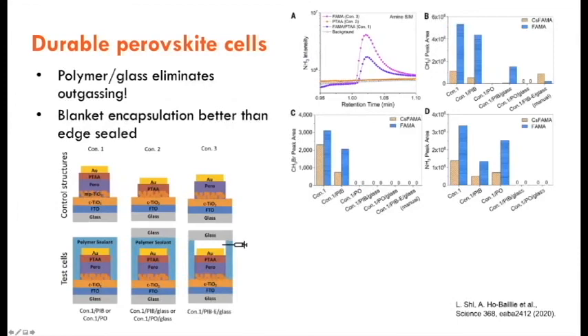So what it does is it creates a pressure-tight environment, to stop the perovskite from outgassing. So why is it important? It's actually the outgassing that drives the decomposition. So if we can stop the outgassing on this track, we can actually stop the decomposition. This is something that we suspected a few years ago because this is an encapsulating scheme that we've used. We managed to get the cells to pass the thermal cycling test required by the standards, but we didn't quite understand why the blanket scheme is better than the void scheme. So we suspected that there's outgassing happening, but this time we're really able to confirm it.